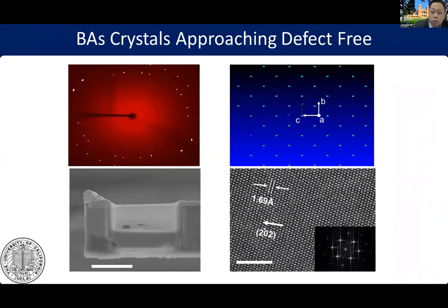In the meanwhile, we did careful structure calibrations. As shown here, the top row is single crystal XRD diffraction patterns and also the reconstructed reciprocal space. From both images, you can see this indicates the whole sample is an entire single crystal domain without dislocations or grain boundaries. The bottom row is high resolution TEM image, shows atomically resolved lattice without defects. So the crystal is really high quality, almost defect free under instrument resolution limit.